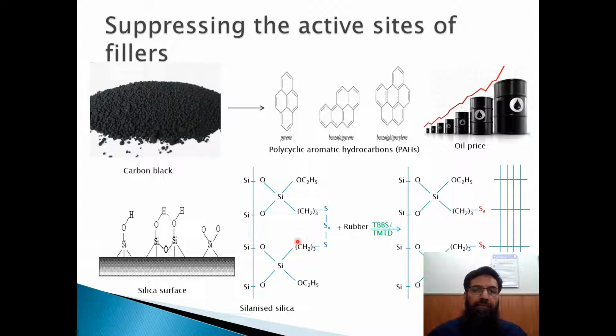And in fact, the carbon black does have some active sites, and those active sites are actually the polyaromatic hydrocarbons which are present on the surface of the carbon black. Due to the presence of these polyaromatic hydrocarbons on the surface of the carbon black, it slightly becomes carcinogenic in nature, because the polyaromatic hydrocarbons are potential carcinogens. So that's why the use of carbon black should be a bit restricted, and the manufacturing should be a bit more controlled, so that we don't have polyaromatic hydrocarbons as the active sites on the surface, because they are not good for the health of human beings. They are carcinogenic. So we do have a potential carcinogenic effect from the carbon black.